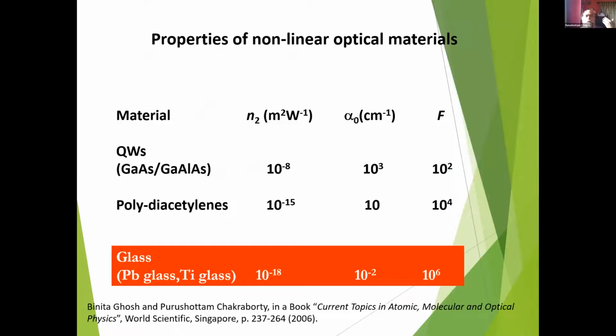Now, take an example of materials like quantum wells, like the gallium arsenide, gallium aluminum arsenide quantum well structure; then the figure of merit is 10 to the 2. The polydiacetylenes are also a kind of material giving you nonlinear optical responses, but the figure of merit is much higher, 10 to the 4. But if you talk about glasses like lead glass or titanium glass, then it can have a figure of merit of 10 to the power 6, which is extremely good for getting nonlinear optical responses or for photonic applications.